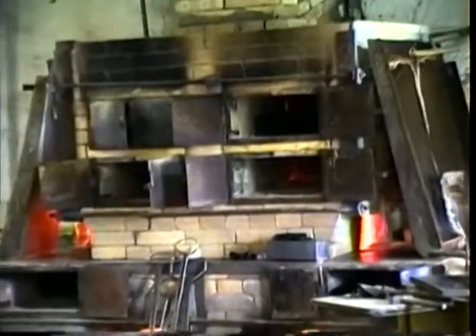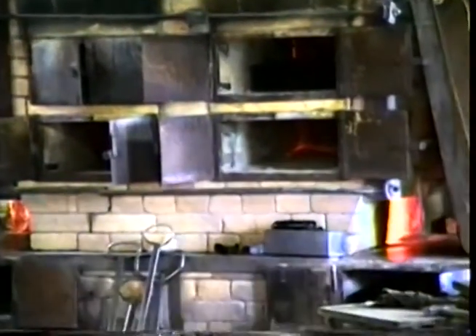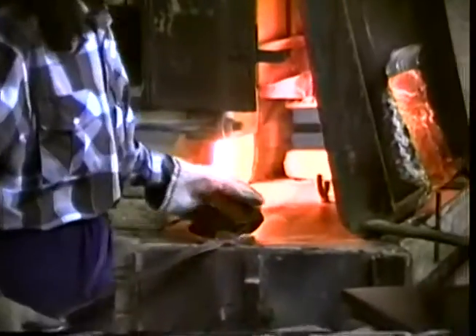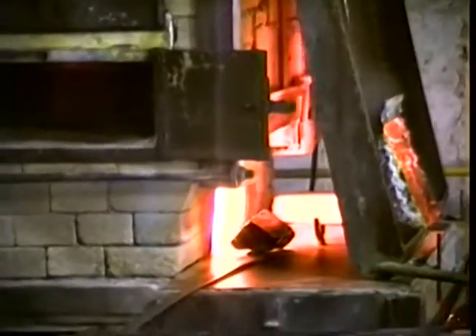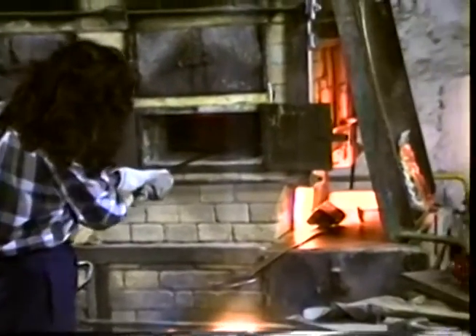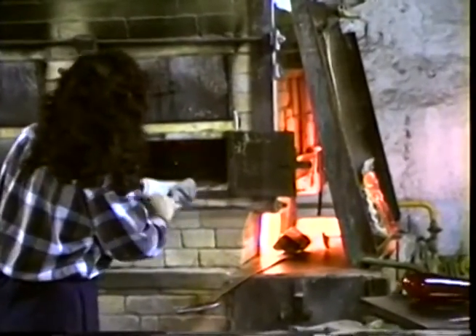In this oven full of chambers, the chunks are constantly rotated to heat them up slowly. They're moved from one chamber to the next, gradually getting hotter, until the final step of putting the hottest one on the hearth of this glory hole to be picked up and heated on the punty. You can see the fork on the hearth for resting the rod while in the glory hole. She will move each of the remaining chunks to its next hottest chamber of the oven.